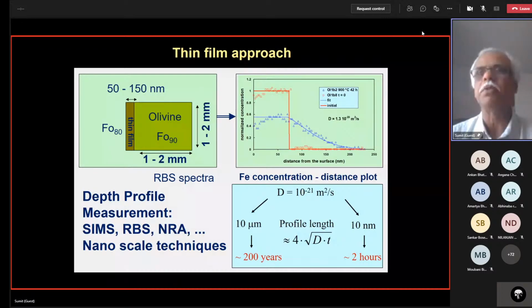Now, what that leads to is what's shown on the bottom right. If you have a diffusion coefficient for some element, some number, let's say 10 to the minus 21 meters squared per second, that may operate in nature and give you a profile over 10 micrometers in 200 years, and over several millimeters in your thin section in several million years. But in the lab, you can get a profile over 10 nanometers in 2 hours. And that's what really changed the picture, because what that means is you can basically set up such an experiment and go to lunch, have a long lunch, and come back and your experiment will be done and you can measure the thing and get your diffusion data.